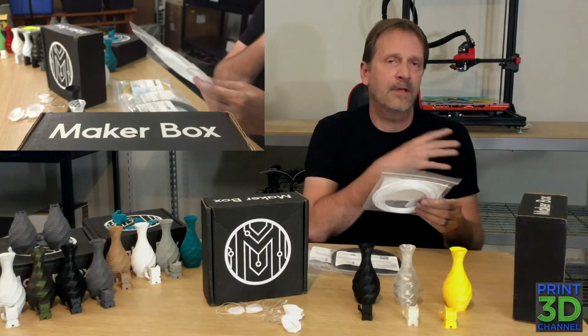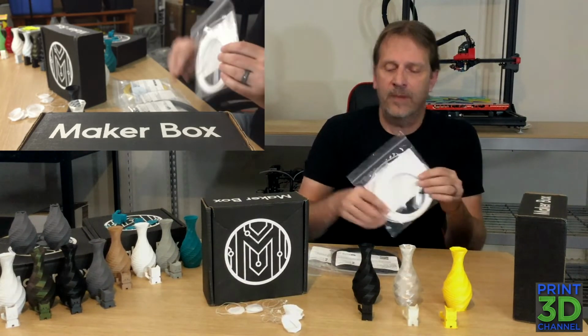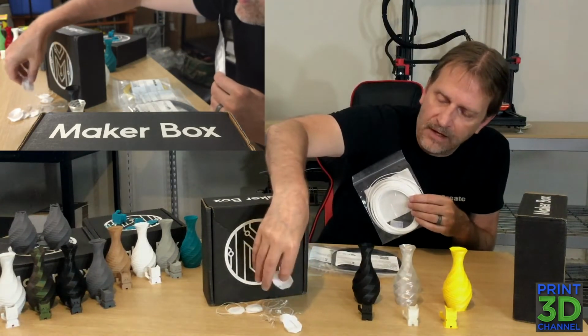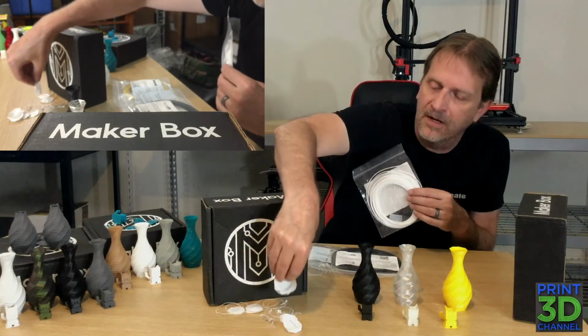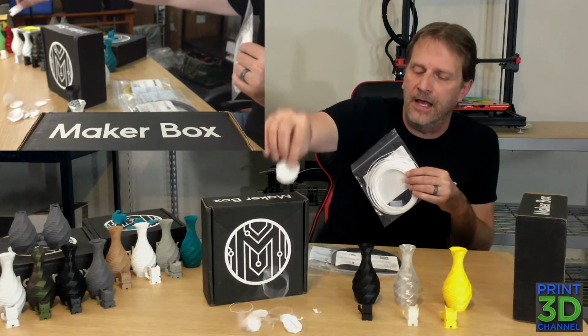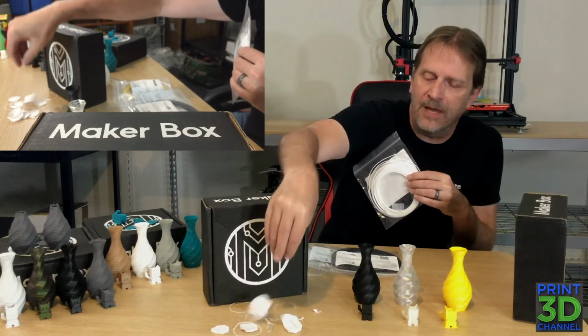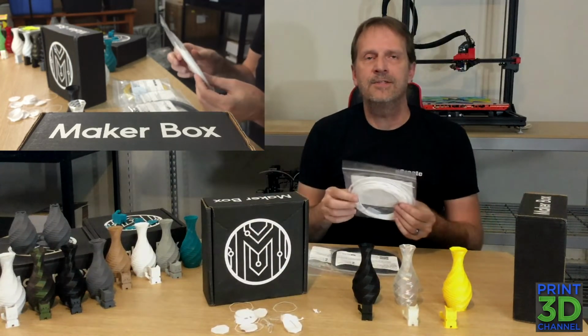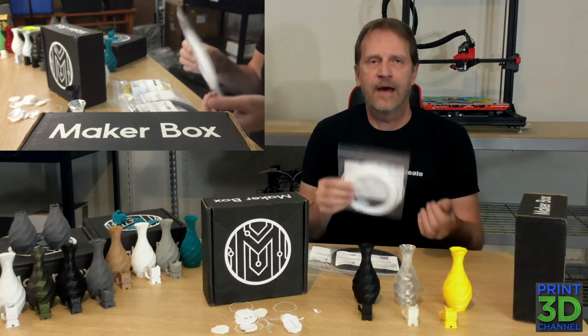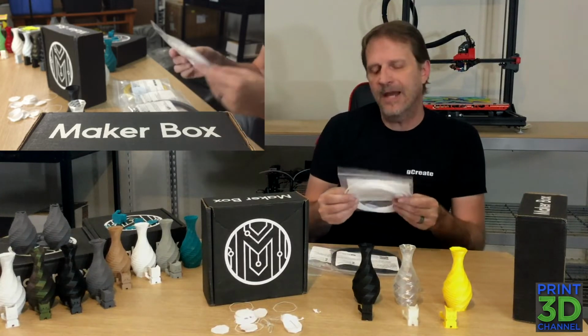And I didn't add the acrylic bed because I went through about 3 or 4 prints. Actually, I'd say that's 5 or 6 prints there of the low poly Rose Twist Vase, and the amount of shrinkage and the amount of non-layer adhesion, and then finally nozzle jams. I mean, a lot of bad things happen.